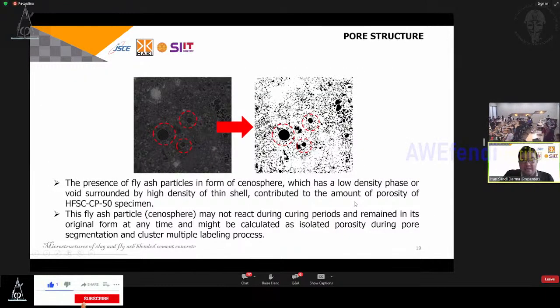Here, as I mentioned before, we will have a cenosphere particle. The presence of fly ash particles in the form of cenospheres, which have a low-density phase or void surrounded by a high-density thin shell, contributes to the amount of porosity in the fly ash specimen. So maybe this is the answer why in some research we found that the fly ash specimen has higher porosity compared to the OPC specimen. Maybe this is the answer.